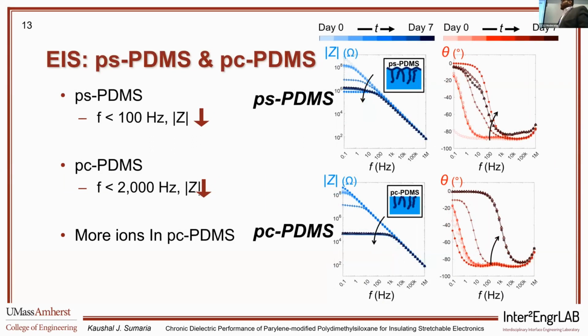For our parylene-shielded PDMS, we see that the ps-PDMS fabricated at a room temperature process shows a behavior which is closer to the ideal parylene or ideal capacitor. It captures less quantity of ion diffusion, whereas the pc-PDMS shows the condition similar to a completely percolated dielectric layer, where it captures a lot of ions inside it.